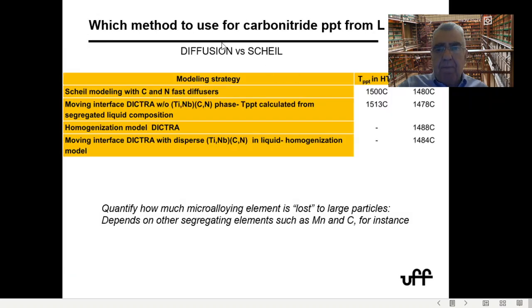Now, when you compare the two methods, the more sophisticated diffusion methodology with the Scheil methodology, we find that the temperature at which the carbonitrides precipitate is very similar, maybe 10 to 20 degrees difference. So if you're looking just at the temperature of when the precipitation is happening, it's not too bad. You can use either one. If you want to really have a better look at what's happening during the solidification, diffusion modeling is much better.